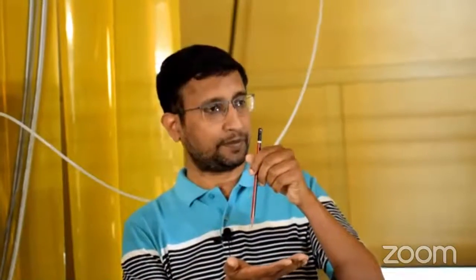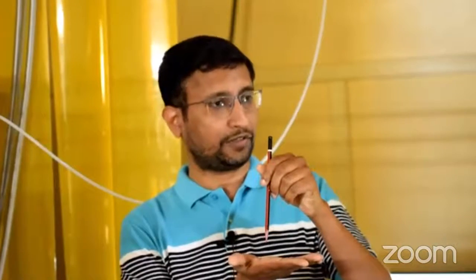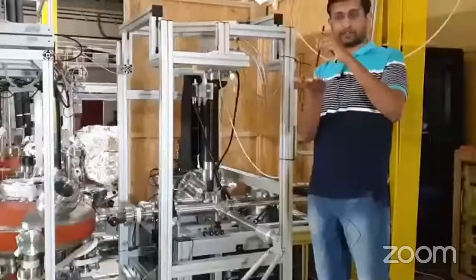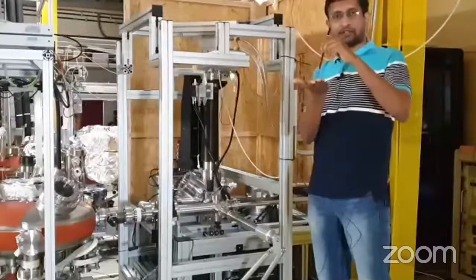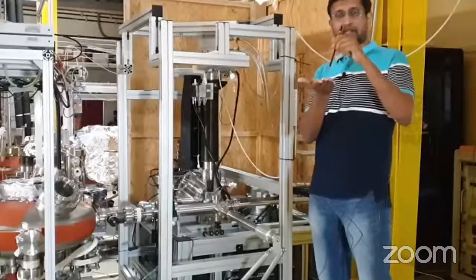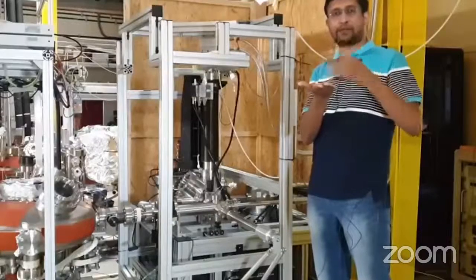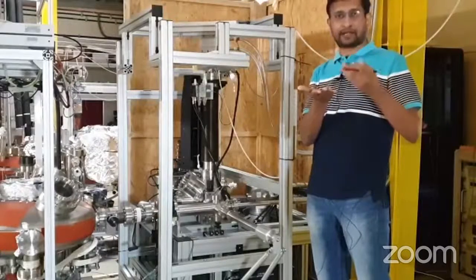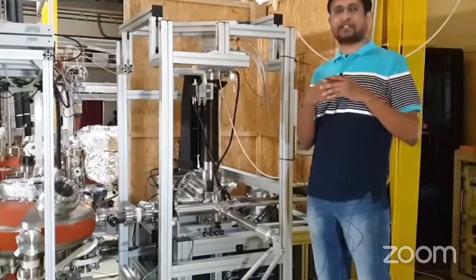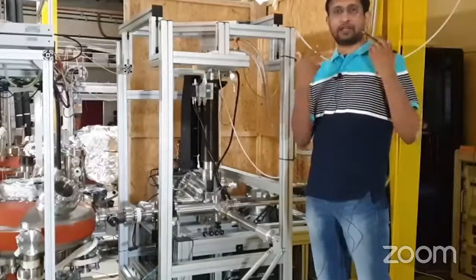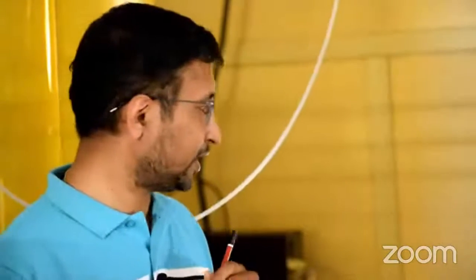And what you do here is you have a tip, it's a tungsten tip, which is very close to your surface, at the level of a few angstroms. And we make this tip scan over the surface to primarily look at the atoms and look at the properties of these atoms as a function of applied magnetic field or applied bias. And this essentially gives us very exotic inferences about the classes of materials that we are probing, whether they are semiconducting, magnetic, or non-magnetic. So with this, I can explain on this computer here how the images are taken.